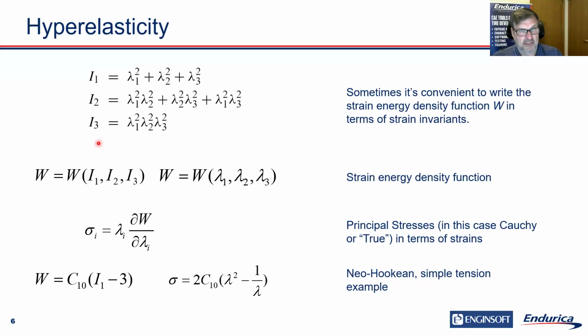That's a function of the strains. In this case, we're using the stretch ratio lambda as a strain measure. It's the final length divided by the initial length. So if you think about putting a 10% engineering strain on a specimen, the lambda is going to be 1.1 for that 10% engineering strain.